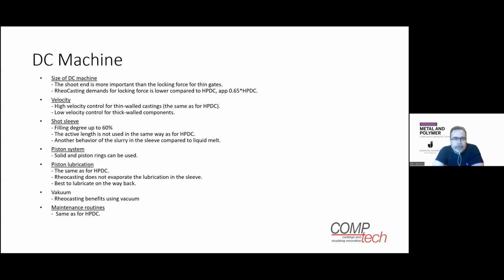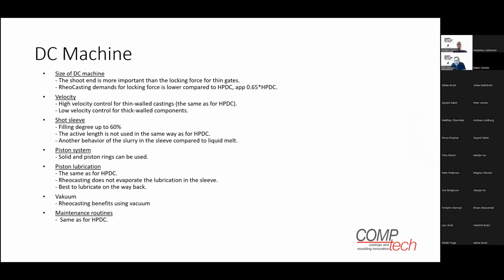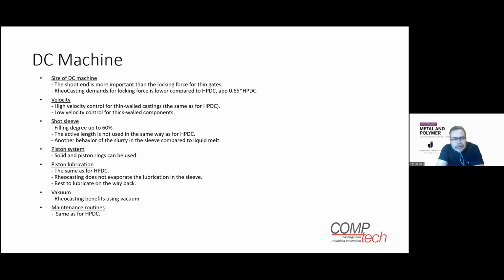So, the die casting machines. First of all, you need to look at the size of the die casting machine. Today, if you have a conventional high pressure die casting machine, you have the projected surface of your shot versus the metal pressure you're going to apply on that surface. That gives you an opening force, and that dimensions what size of die casting machine you are using. What we have learned is that when you do this calculation, you can apply a factor of approximately 0.65 and still be able to cast those parts in that same locking force machine. This is also somewhat geometry driven, but in general, 0.65 is safe to calculate.